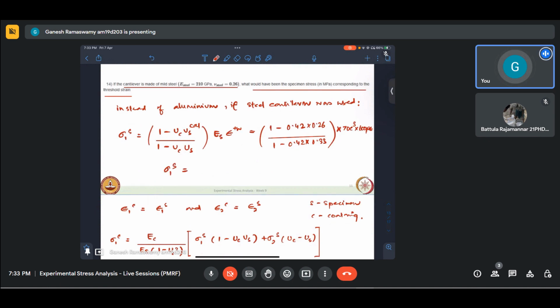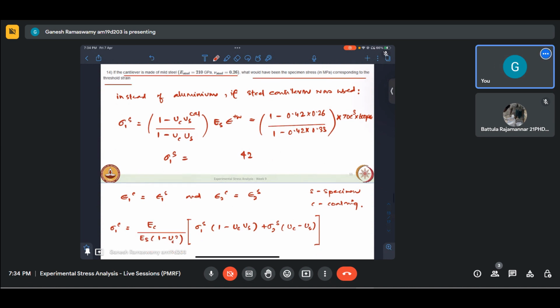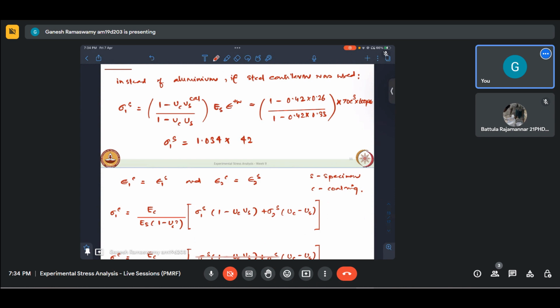So what does this come out to be? Instead of 42 MPa, which we got, it will be 42 into this quantity, which was earlier 1. That will no longer be 1. So it will just get corrected by some factor. What is that factor? 1 minus 0.42 into 0.26 divided by 1 minus 0.42 into 0.33. This is 1.034 into 42, which comes out to be 43.43. So if the cantilever was made of steel, then the specimen stress would have to be 43.43 in order to achieve the same threshold strain.